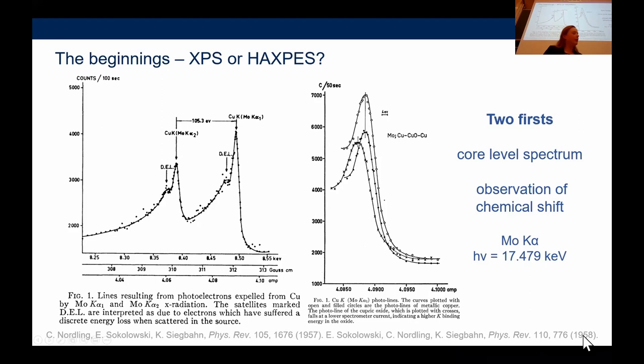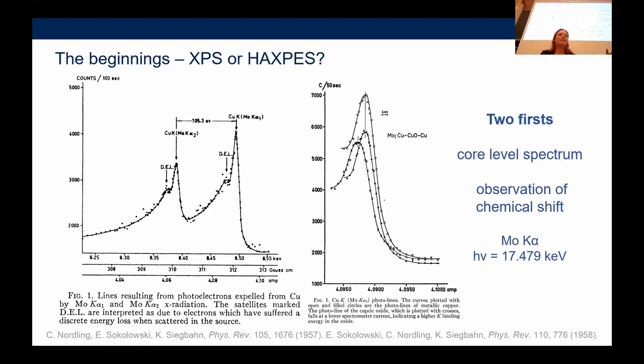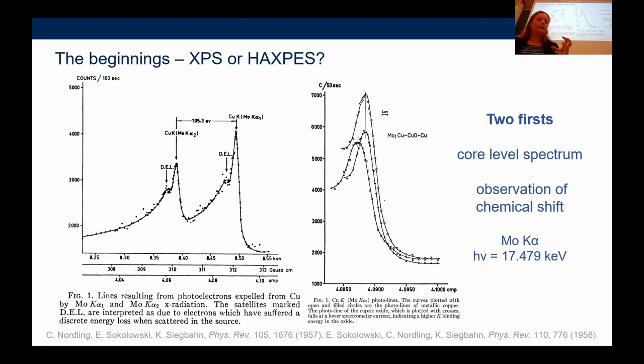For those into photoemission history: we generally think of soft X-rays, with aluminium and magnesium K-alpha as the starting point. But actually the first two spectra Siegbahn's group published used molybdenum K-alpha as the excitation source — that's over 17 keV, definitely in the hard X-ray range. We would never use those energies nowadays for various reasons. The first core spectrum was copper 1s collected with molybdenum K-alpha, and it was also used for the first observation of the chemical shift — this idea that photoemission lines change energy depending on local chemistry. So hard X-rays were there from the beginning.